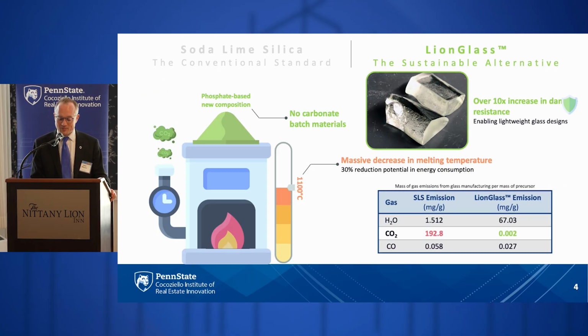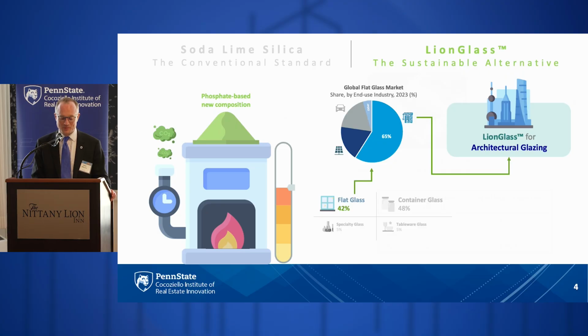The table down here at the bottom shows the emissions, milligrams of CO2 emitted for every gram of glass produced. And you can see that for soda lime silicate, this is about 193 milligrams per gram of glass, whereas with LionGlass, just from the batch to melt conversion process, that's basically atmospheric CO2.